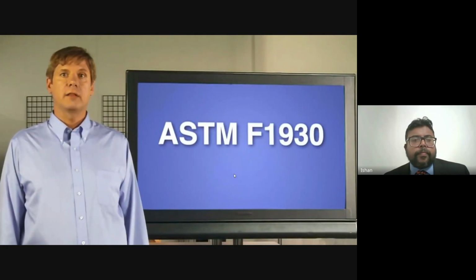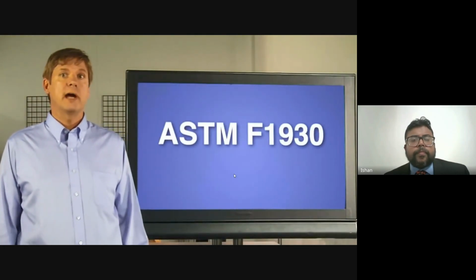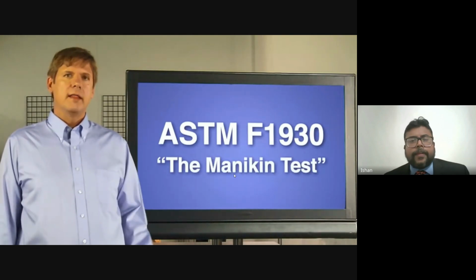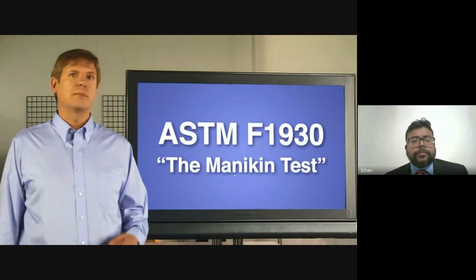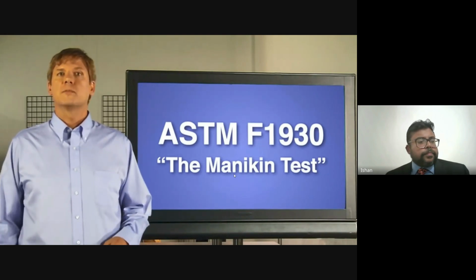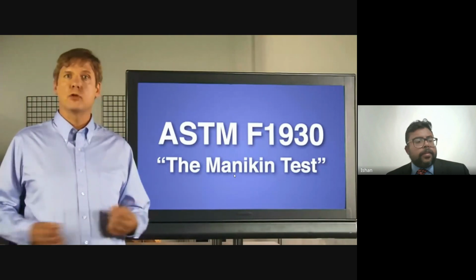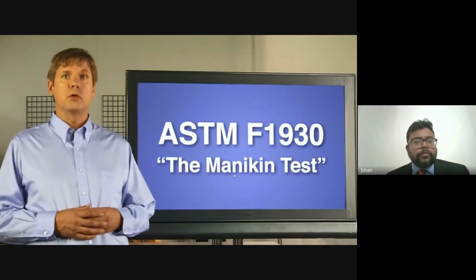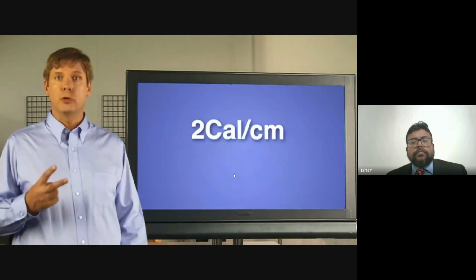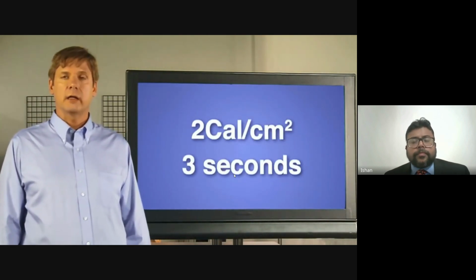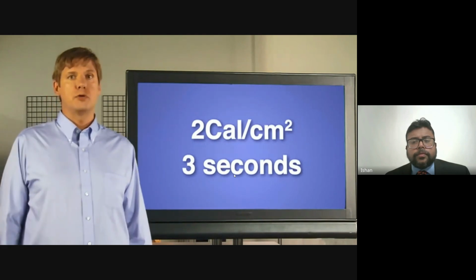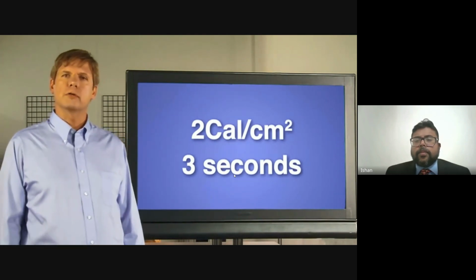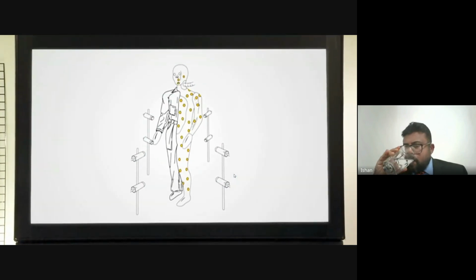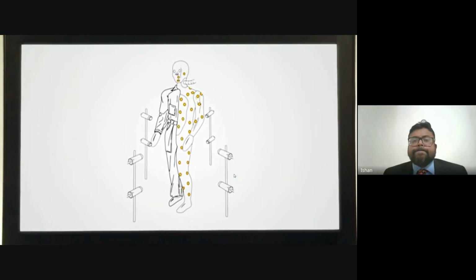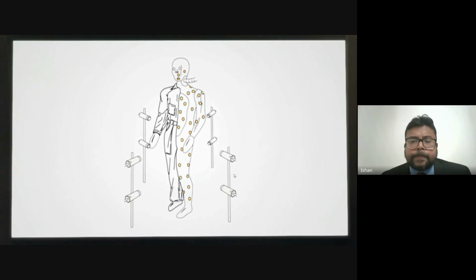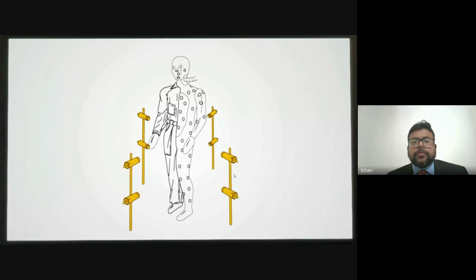ASTM F1930, more commonly referred to as the mannequin test. This test method is designed to evaluate the protective performance of material when exposed to simulated flash fire in laboratory conditions. The test is performed using an exposure heat flux of 2 calories per square centimeter per second for 3 seconds of exposure time. Here's how the test works. The mannequin has over 100 heat sensors distributed uniformly around its body. The mannequin is surrounded by at least 8 propane burners.